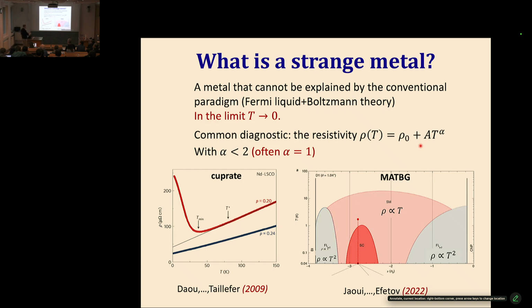Okay, so as we saw, cuprates have a very wide range of temperatures where the resistivity is linear as a function of temperature, but that gets cut off. It's below some temperature of a few tens of Kelvin. The really special thing is the limit T goes to 0. That really tells you something about the nature of the quantum ground state of the system. And to be able to sustain this behavior all the way down to the lowest temperatures, the ground state has to be fundamentally different from a Fermi liquid. So that's why we want to really be able to make a sharp distinction. We really want to insist on this condition.